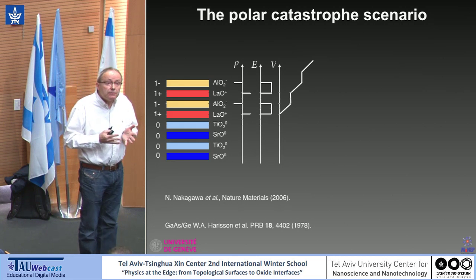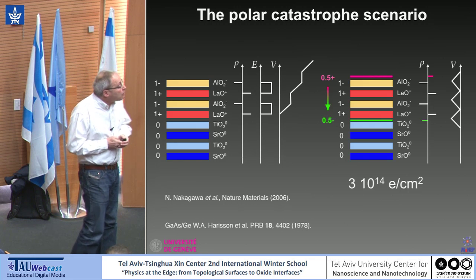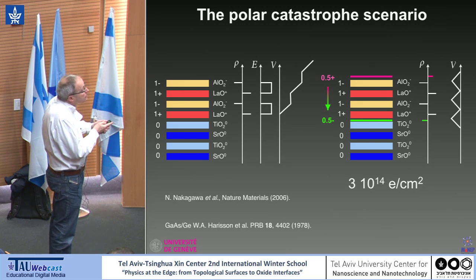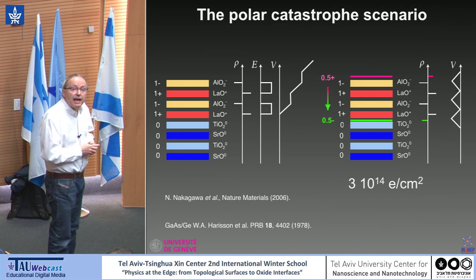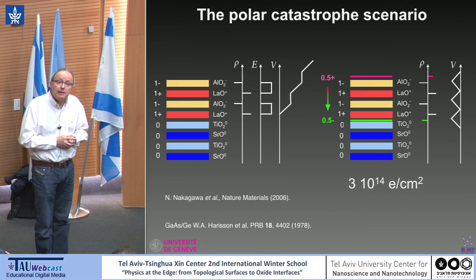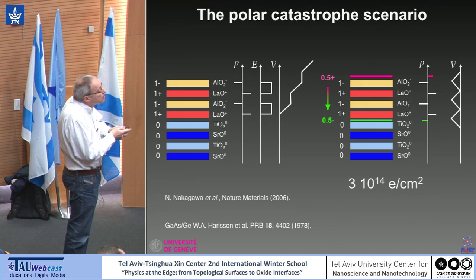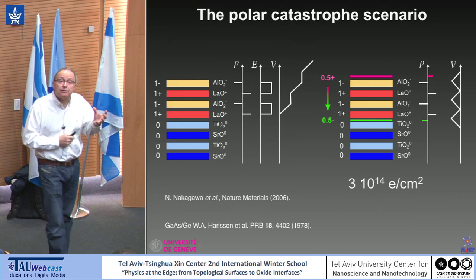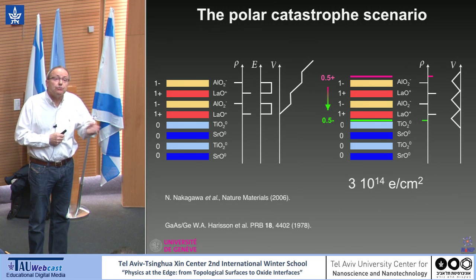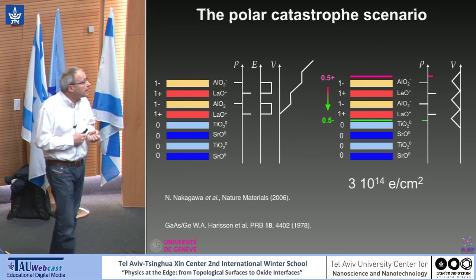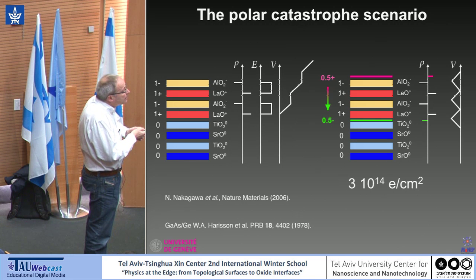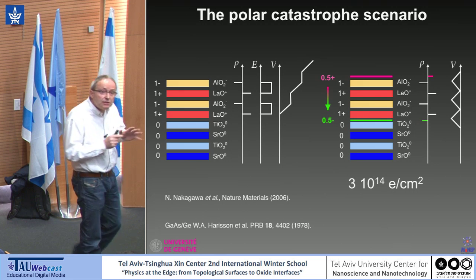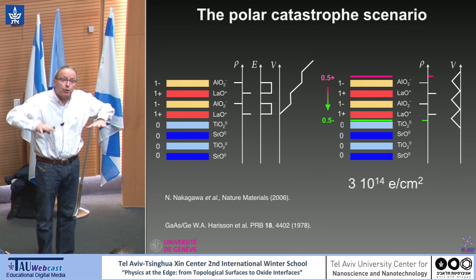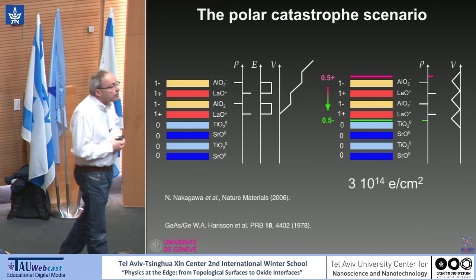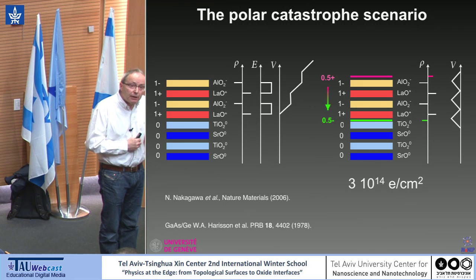Now, at some point, the system has to do something, and one possibility is to transfer from the surface to the interface half an electron per unit cell. If you do this, then the potential is not diverging anymore, but is oscillating around 0. And these electrons can go in the titanium 3d band. If you make a calculation, you find that the sheet carrier density, which is quite important, the density of carriers per unit area, is 3×10^14 per square centimeter. I will come back to this.